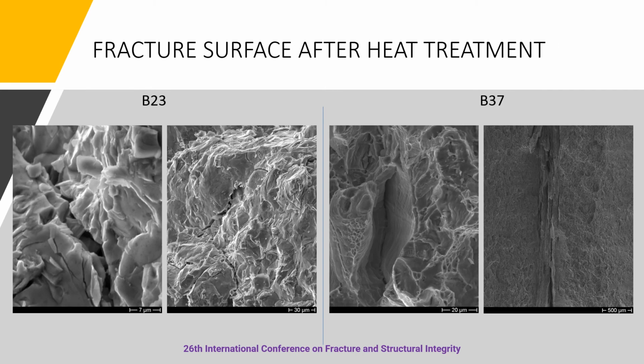Coming to the fracture surface following the tensile test after heat treatment, it can be seen that while B37 has a similar kind of ductile fracture as before, B23 shows a very brittle fracture. This is because after heat treatment it developed intermetallic phases which were more brittle in nature. Also, after heat treatment, B23 developed secondary cracks in the alloy that assist the fracture mechanism.